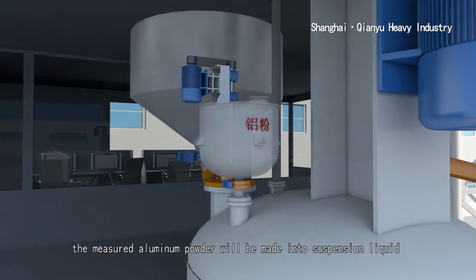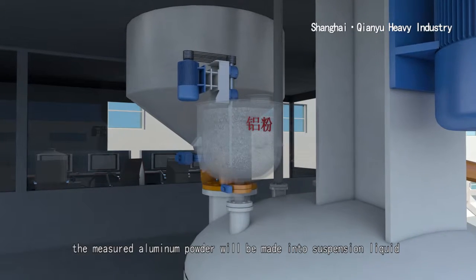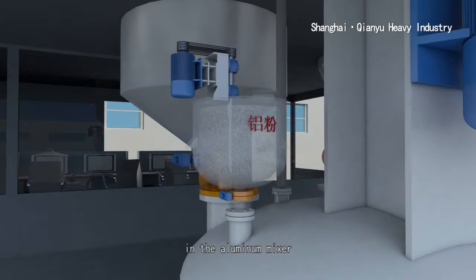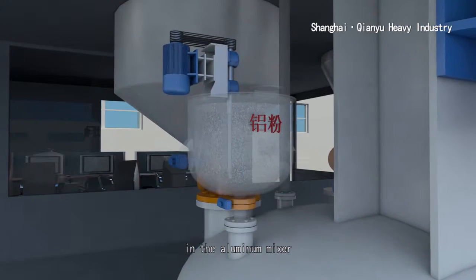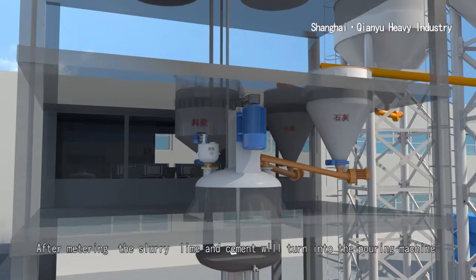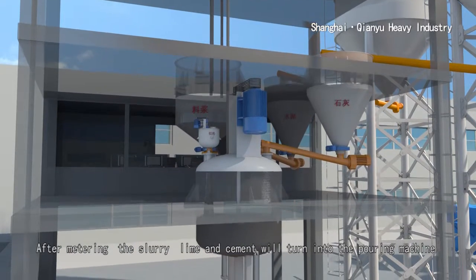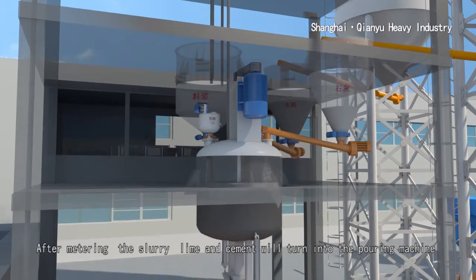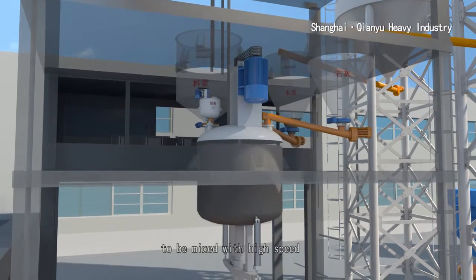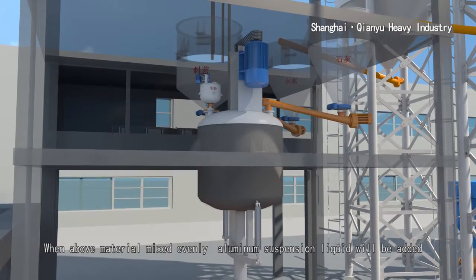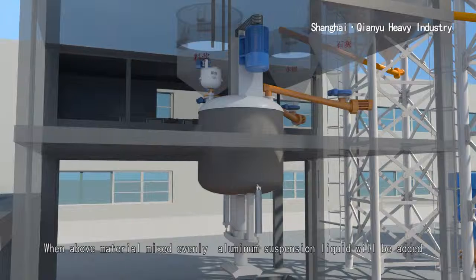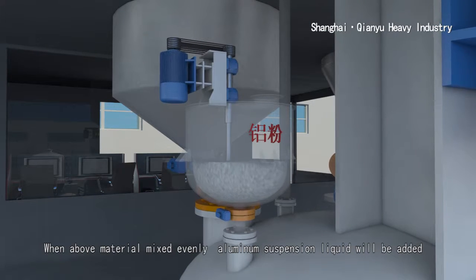The lime and cement will be transported to the powder scale silos by screw conveyors. The measured aluminum powder will be made into suspension liquid in the aluminum mixer. After metering, the slurry, lime, and cement will turn into the pouring machine to be mixed with high speed. When above material mixed evenly, aluminum suspension liquid will be added.